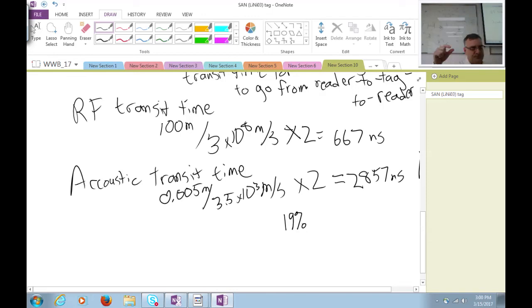So despite the fact that the signal in the acoustic medium is only traveling a half a centimeter, if I try to interrogate this tag from 100 meters away, of the total transit time, less than 20% of the time is actually RF. It takes me 1/5 the time to go to the antenna and back than it does to actually stay within the acoustic medium, hit reflector bars that encode information, and then come back. So you see why this is a very effective technology for doing some interesting sensing applications without batteries, right?